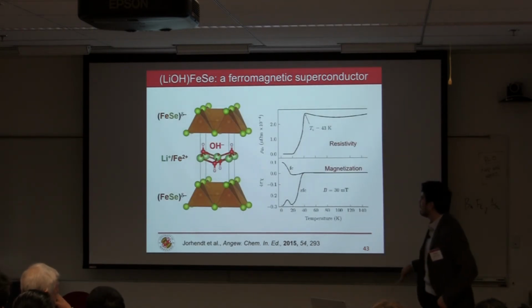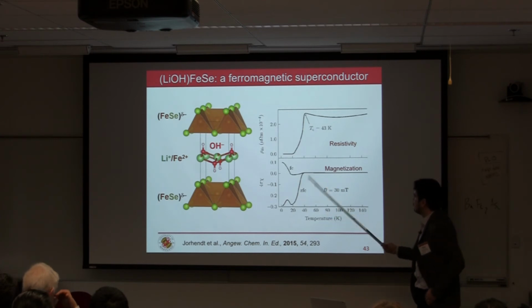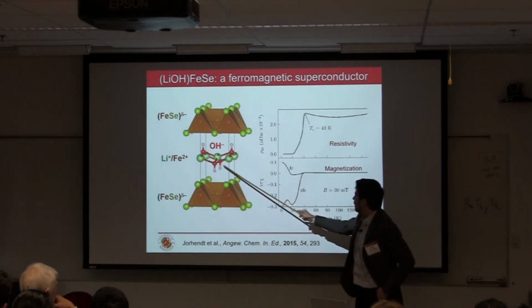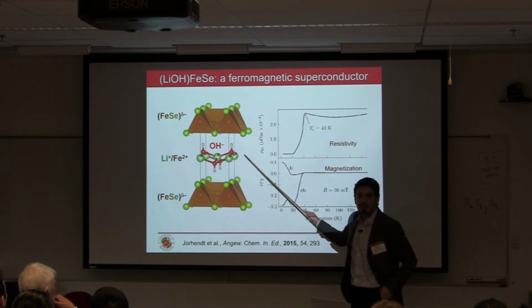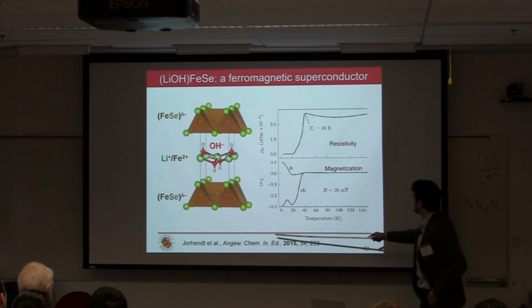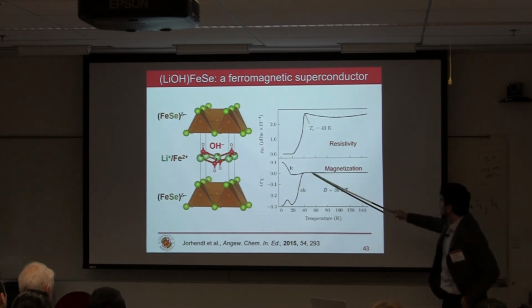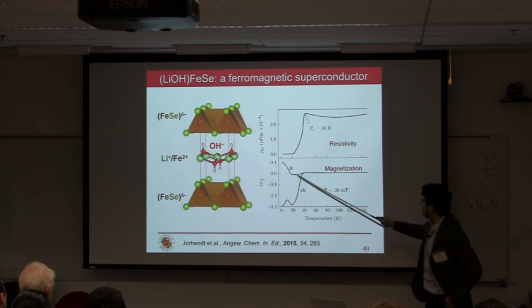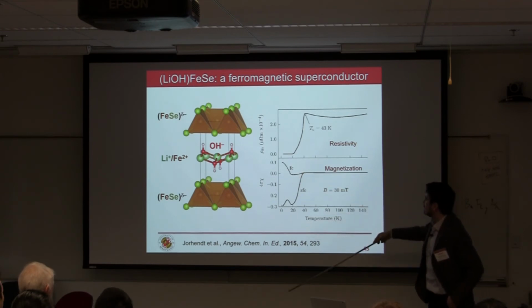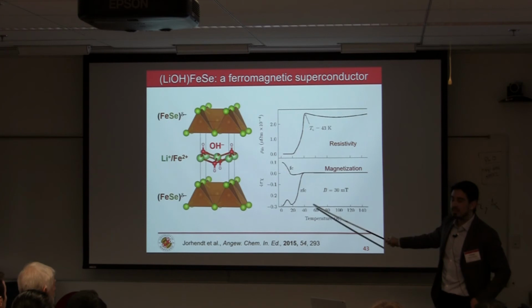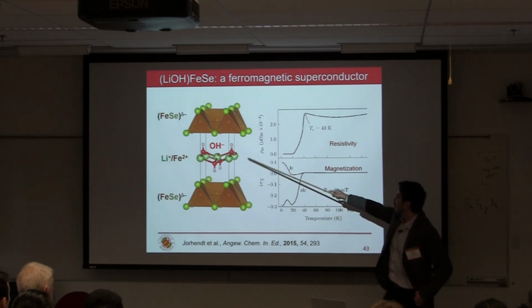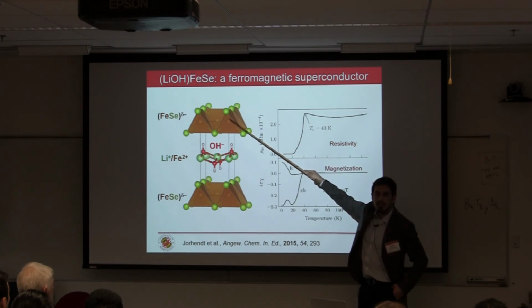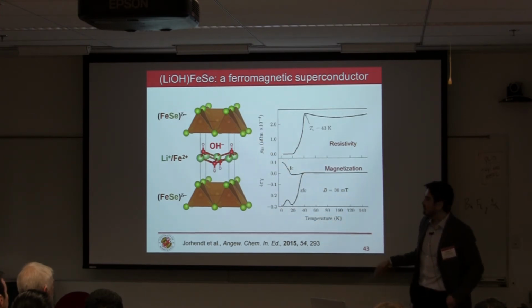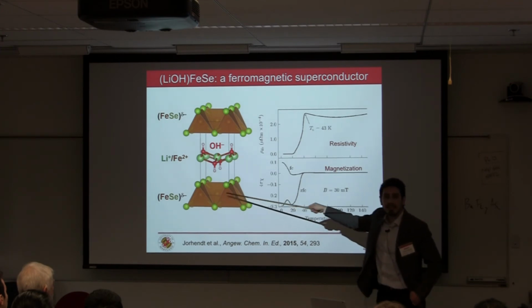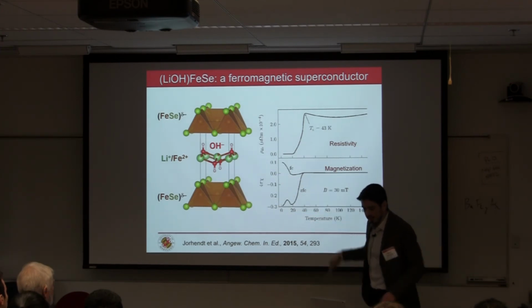Another reason I got interested in these selenides is that you can intercalate different species in between, including magnetic cations like iron. And Dirk Johrendt found that upon hitting its critical temperature, from magnetic susceptibility in the field-cooled curve, you can get this anomaly here. And Johrendt postulated that this was an example, possibly, of ferromagnetism existing in this layer, proximate to a superconducting layer here. And they postulated that you could form the so-called spontaneous vortex lattice within the iron selenide because of the magnetism in the hydroxide layer.